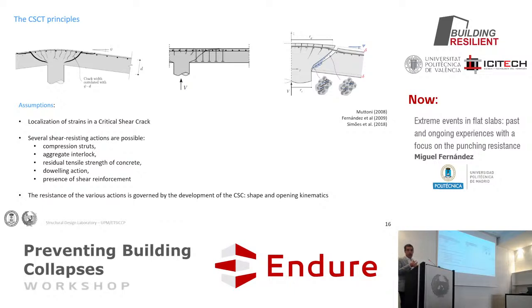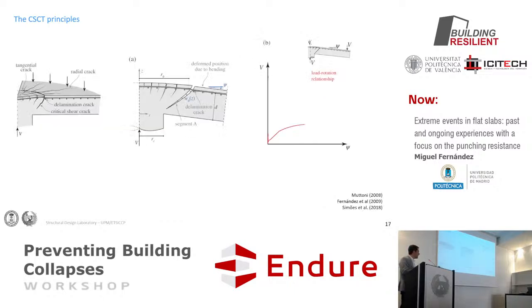Residual tensile strength, well, they are related. One is mode 1 and the other is combined mode 1 and mode 2. That one acts just on top, and eventually, if shear reinforcement is available, also the contribution of shear reinforcement. So it's very simple. You consider you have localization, which is true. You adopt a shape and a kinematics for that, and then you just integrate the contributions, and you will see what the resistance is. These simple ideas are what we're seeing here.